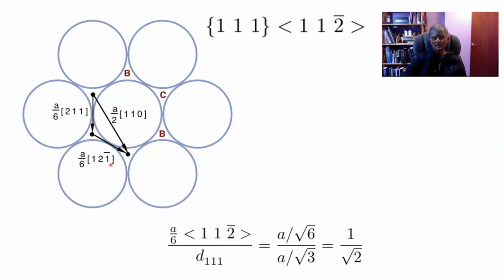And we had a shear strain as a consequence of 1 over root 8. Now, in this case, we are passing the Shockley partial on every adjacent 111 plane. So the displacement is a/6 <112>. And the distance over which that displacement happens is the spacing of the 111 planes. So the magnitude of this is a over root 6, and the magnitude of the spacing is a over root 3. And therefore, the shear involved is 1 over root 2, which is approximately